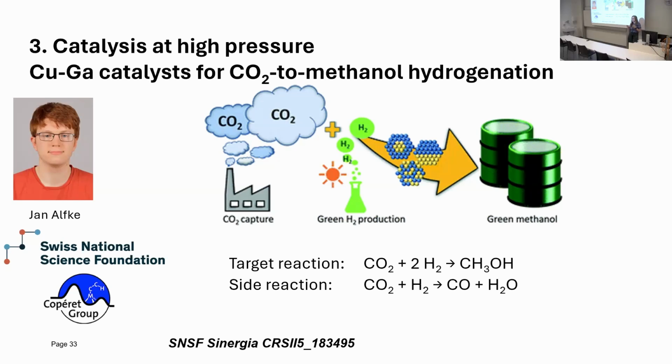And we were looking at CO2 hydrogenation to methanol. We wanted to understand the strange activity of gallium as a promoter to copper, because everybody knows zinc is always a good promoter, it increases the selectivity for methanol. But for gallium, there was not so much research, and the research was quite contradictory. So it was not clear why for some catalysts the activity was very high and for some was nothing special.